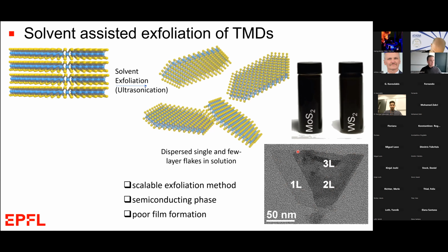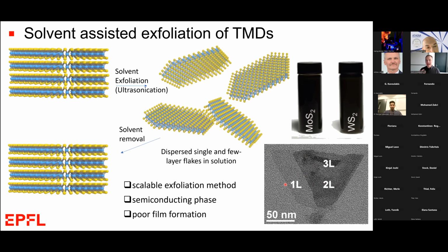But there's a lot of advantages when it comes to performing this solution-based or liquid-based exfoliation technique. However, when we try to make films of this over a large area to test the photoelectrochemical performance, we ran into a big problem. When we tried to remove the solvent, the van der Waals forces between these large area basal planes cause rapid restacking and aggregation of these flakes and really make poor films.